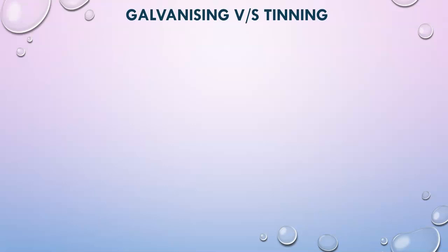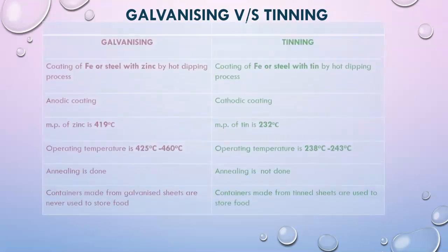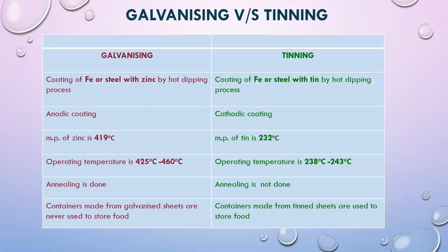Let us compare the two processes, galvanizing and tinning. Galvanizing is coating of iron or steel with zinc by hot dipping process, while tinning is coating of iron or steel with tin by the hot dipping process. Galvanizing is anodic coating, while tinning is cathodic coating. In galvanizing, the melting point of zinc is 419 degrees Celsius, while the melting point of tin is 232 degrees Celsius. The operating temperature for galvanizing is 425 degrees Celsius to 460 degrees Celsius, while the operating temperature range for tinning is 238 degrees Celsius to 243 degrees Celsius.